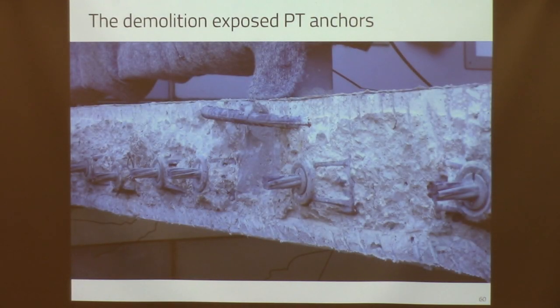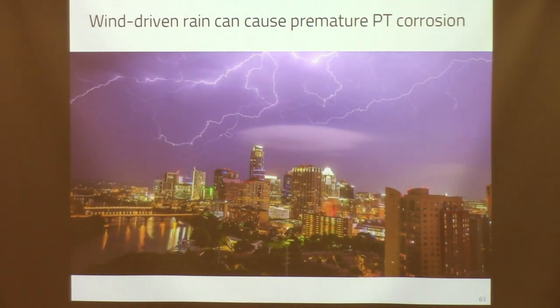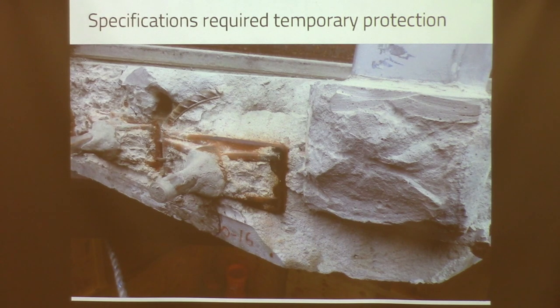So we've got these exposed PT anchors, which was a concern to us. How long were they going to be exposed before we cast the new concrete back? Although Austin is not near the ocean, it does get rain and thunderstorms quite often. So we were concerned about getting water driven from rain into these PT anchors. And in fact, you can see in a very short time, you'll see some almost flash rust, ferrous oxides that develop. That's that orange color.